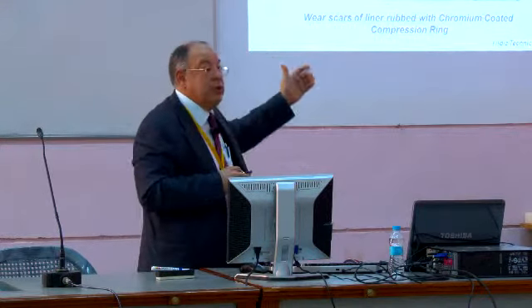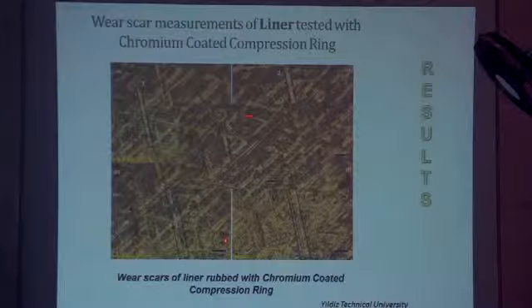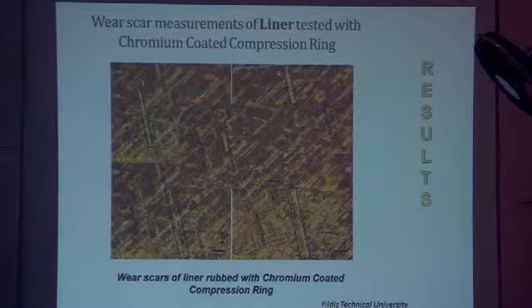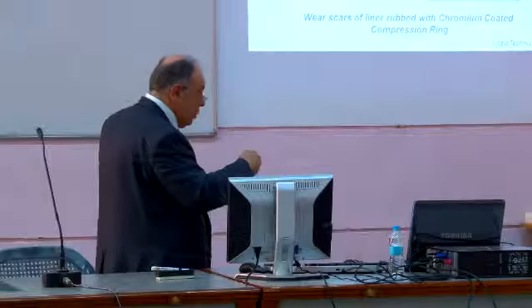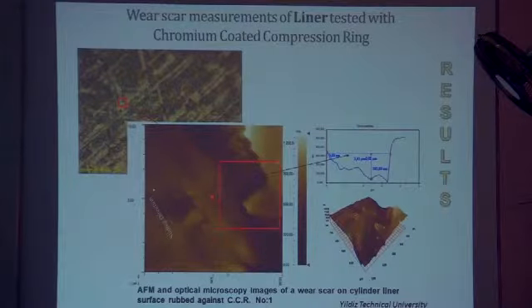I have also zinc phosphate coated ring. This is optical microscopy, where you see on the liner of chromium coated ring we have additive layers. Five points are measured by AFM, and you see number 1 and number 2 shown here. In number 1 you see the white patch here, and there is a white patch here also, but there are dark patches here. So these white patches are layers, are additives on the surface.